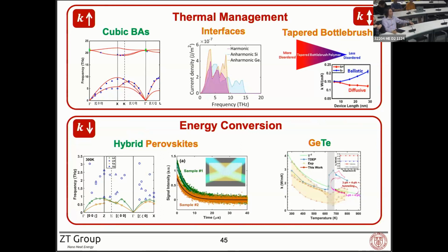But if I think about it for the molecular dynamics simulations, it always includes the full order anharmonicity, right? But it still has the temperature effect. When you have a different temperature, you get... But the potential is always the same, no? So the potential that determines the forces on the atoms does not depend on temperature. So if you have an exact expansion of the potential, the forces that you get from a dynamic don't depend anymore on the temperature. Only if you truncate the Taylor expansion up to a finite order, that depends on how much the molecular dynamics is sampling around your equilibrium point.